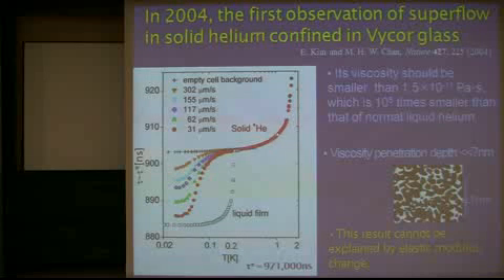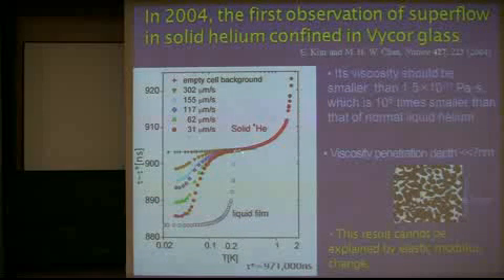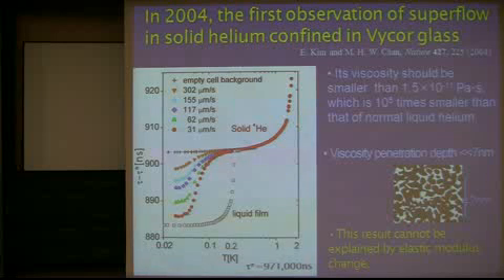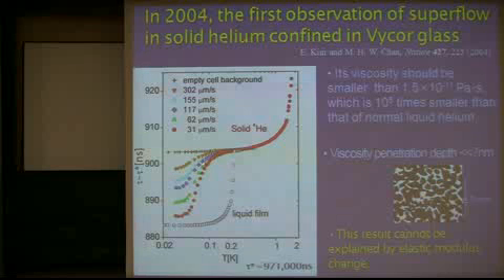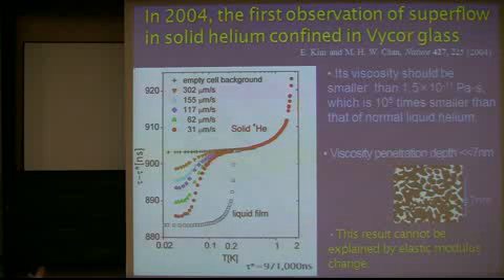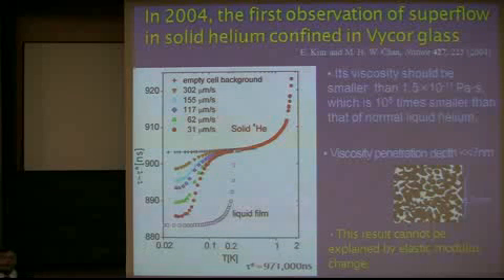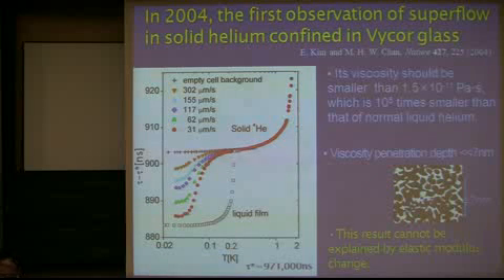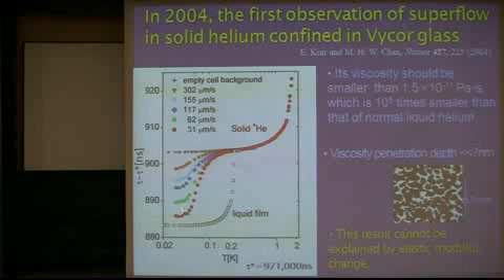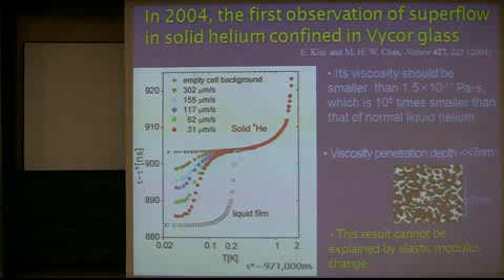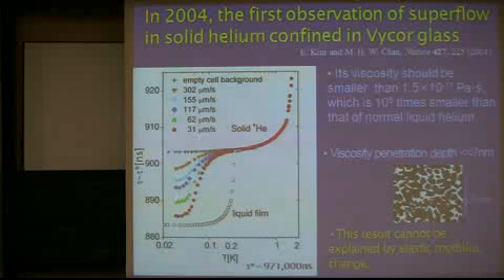But this just decreases linearly, and if there is no missing rotational inertia, then it will just follow the empty cell background, no trend, right? However, what we have seen is the red data with the minimum oscillation velocity. We found a decrease in the resonant period. That means we have something missing inside the torsion cell, a missing rotational inertia. And if you increase the AC oscillation velocity, that total reduction is strongly suppressed.